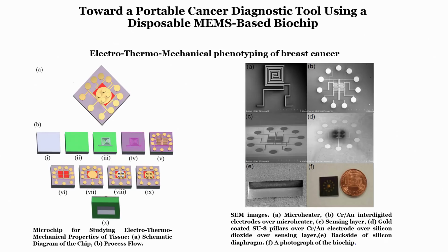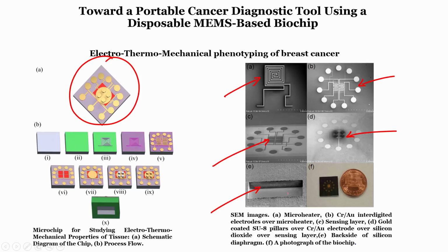Okay. If you see the slide, our goal is to understand how we can fabricate this particular chip. This chip is indicated with a micro heater. This chip is indicated with interdigitated electrodes. On the interdigitated electrodes there are piezoresistive materials, and on that we have another insulator. On that there is a gold pad, over which there are SU 8 pillars which we made conductive. On the back side of the chip there is a diaphragm, and I will tell you the role of the diaphragm when we understand the fabrication of the complete chip.